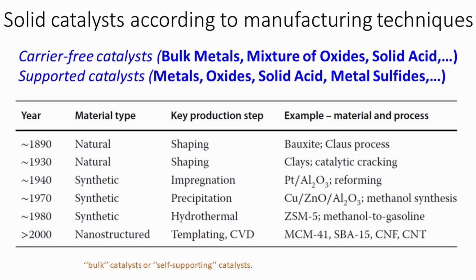The development of the manufacture of solid catalyst synthesis is summarized in the table. The first solid catalysts consisted of supports and an active phase available from nature. Bauxite and clays are examples of active phase, while, for example, Kieselguhr is a natural source of silica support material. Using sol-gel chemistry, synthetic support materials have been developed. Application techniques for the active phase based on impregnation and drying were developed during the 20th century. Hydrothermal synthesis can be important for synthetic zeolites such as ZSM-5.